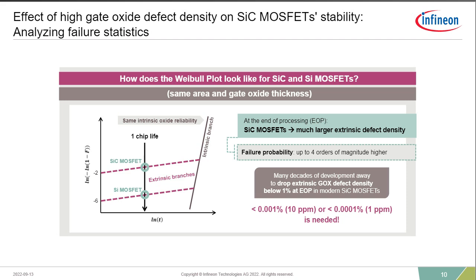So it becomes very important to develop a process where you can filter out these extrinsic defects that exist in the raw base material. And Infineon has a particular answer for this for you, which we'll cover in the coming slides. So just a difference in ppm rate, you're talking from 1 to 10 ppm. And silicon carbide will get better over time, and the amount of defects in the product will reduce, but it will take some time. You're looking at 5-6 years before you really see closer parity in terms of the quality of the base material.